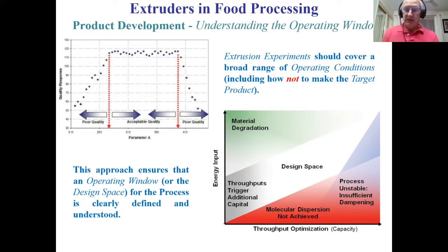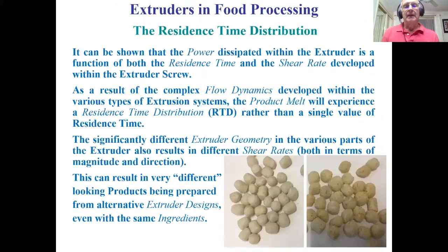And this is critical when we start to look at the scale-up exercise, because the residence time directly influences how the viscous power dissipation directly influences how the product cooks, as we've discussed so far. And so this allows us to make very different looking products, as you can see here, even from the same extruder, even with the same ingredients on the same day, by changing the detail of how we're running the machine. And so a broad range of products can be made. Some of these might be acceptable, some not, some may be preferable to others, but it makes the whole exercise quite challenging, but very interesting.